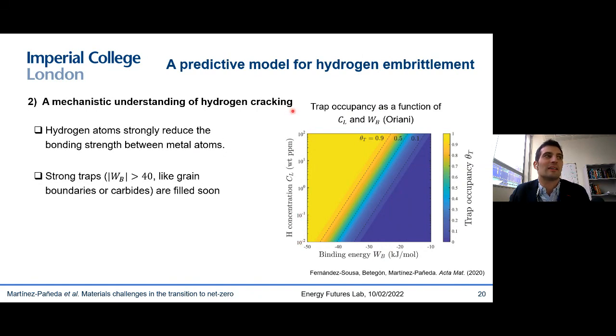There's an anonymous question about how binding energy affects the embrittlement and the scope of solid state hydrogen storage. Go back to this map. This is basically what we want. There's kind of a dual effect, and there's a bit of a discussion there, right? So this is Oriani's equilibrium, which is perfectly valid for most scenarios. And then here you have the lattice hydrogen concentration as a function of the binding energy, and this is the trap occupancy. So for a given hydrogen concentration and a given binding energy, what is the trap occupancy?